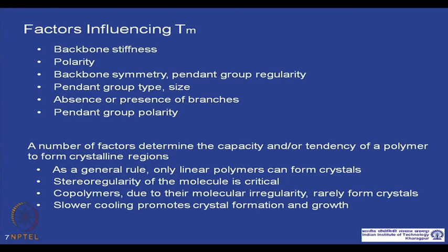Copolymers, we are talking about random copolymers, due to their molecular irregularity rarely form crystals. Obviously, if you cool the polymer melt slowly, then the polymer chains get more time and they can crystallize, the crystallization takes place easily, or the crystallites can grow to a bigger size.